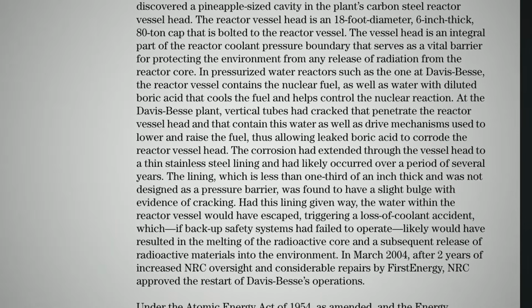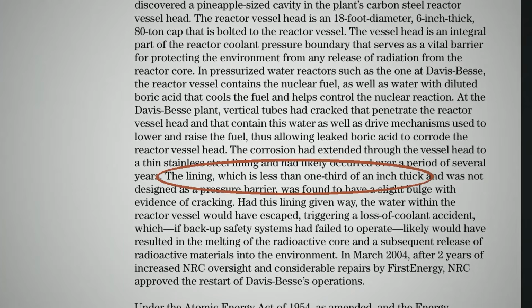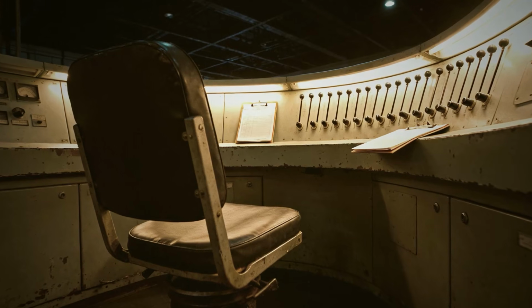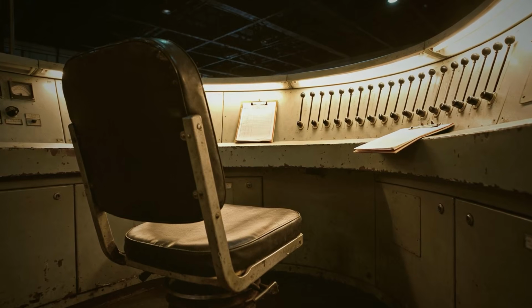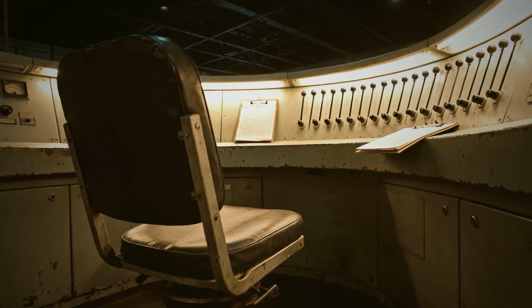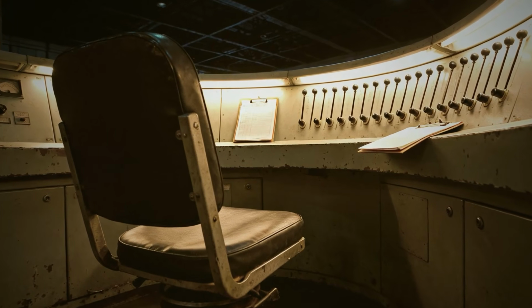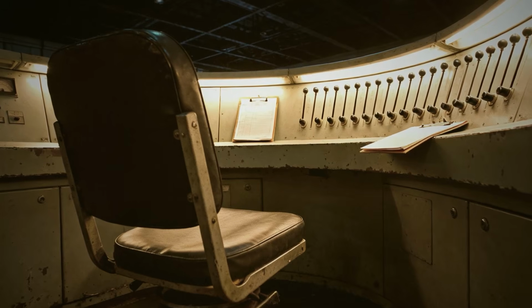I want to be precise about that last layer because the reports are not identical, and I am not going to smooth that over for you. The Government Accountability Office describes the liner as a thin stainless steel lining, less than 1/3 of an inch thick. Other technical accounts of the same event give a thinner figure at the worst point, as low as 3/16 of an inch. The two numbers describe the same piece of metal measured different ways.